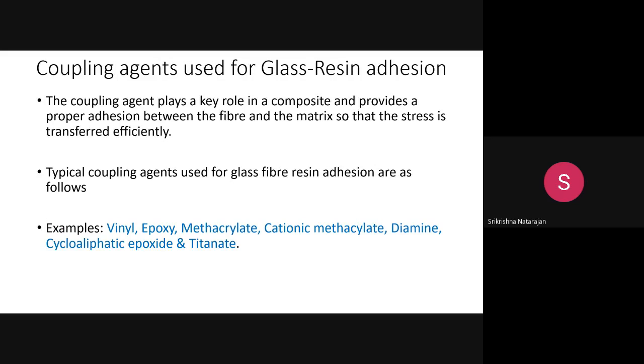If you see the coupling agents used in the sizing application, there are a number of coupling agents. All these, if you observe, are basically resins. So there are multiple coupling agents for promoting this adhesion. They are called vinyl, epoxy, methacrylate. Many thermosetting polymers are there. You see epoxy and vinyl, these are thermoset polymers. Then acrylic polymers like methacrylate, cationic methacrylate, diamine, cycloaliphatic epoxide, titanate. There are many coupling agents that can be used so that the glass and the resin adhesion will be promoted.